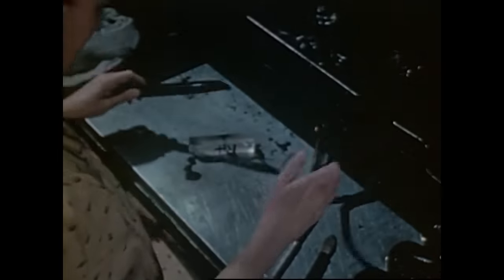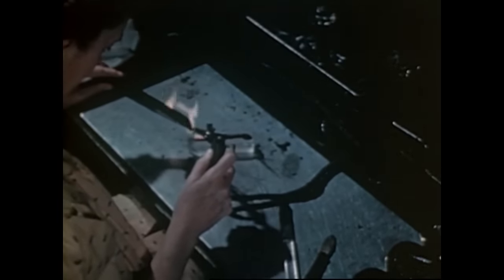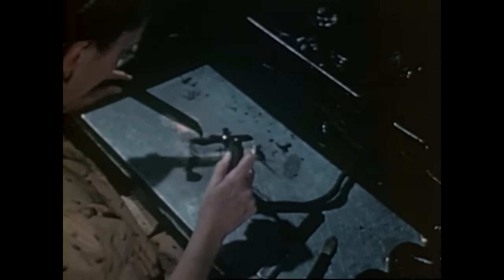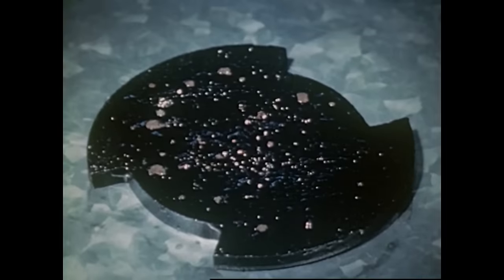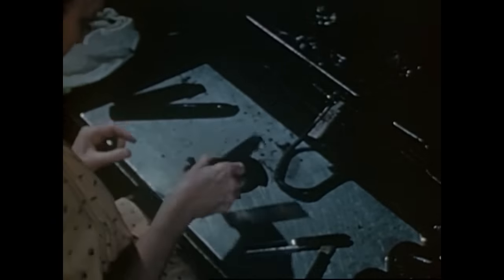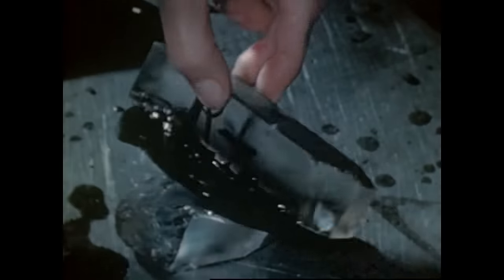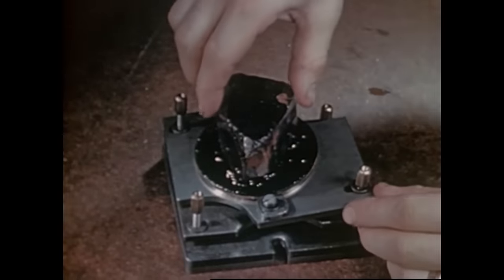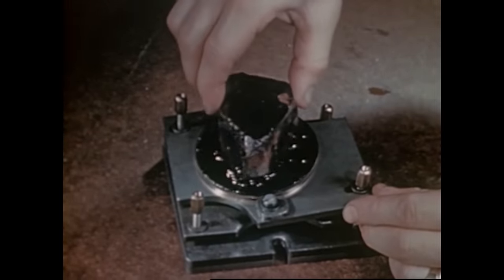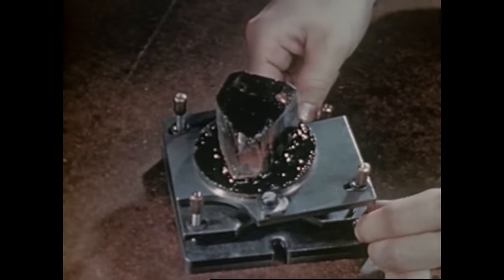The warmed quartz is taken from the oven, coated with shellac and hot cementing compound, and its piezoelectrically negative side mounted down against the faceplate of the jig. For accurate determination of the angle for cutting the wafers, it is necessary to provide for both easy adjustment and firm clamping of the quartz. It is mounted on a jig, such as the one shown, where the quartz may be oriented in any direction. It is to be finally locked in just the right position for the saw cut.